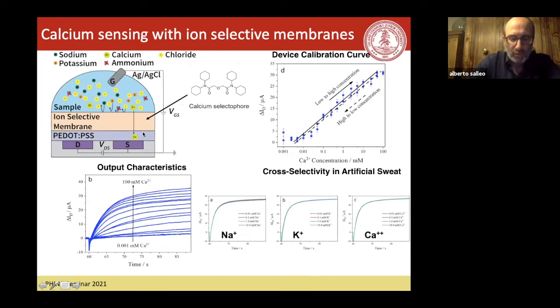I have my transistor here. On top of it, I have my electrolyte. I put a pulse on the gate. With a positive pulse, the cations will try to cross the membrane. The only cation that can cross the membrane is calcium. So I get a change in conductance as a function of the concentration of calcium.